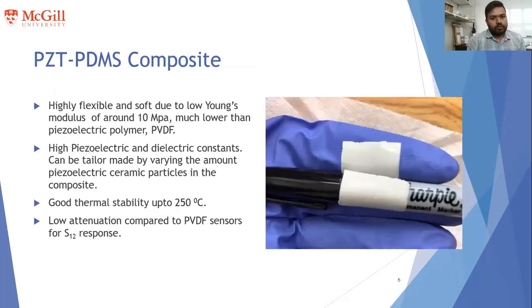The PZT PDMS composite which we prepared is very soft and flexible, which you can see from the figure, where it can roll over a pen or pencil. It has a very low Young's modulus, in the order of 10 MPa, compared to another piezoelectric polymer, PVDF, which has a Young's modulus of around 2 or 3 GPa.